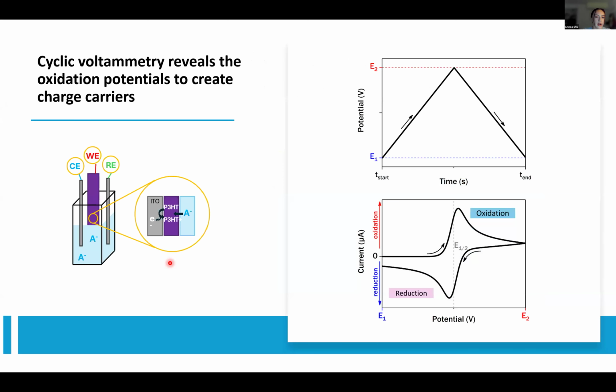So to do this, we can take our cell and perform experiments such as cyclic voltammetry, where we are sweeping the voltage and measuring the resultant current. And where we have peaks indicate the potentials at which we are oxidizing the polymer. So on the forward, our positive sweep, here we have the oxidation peak, and this is where we expect to see anion intercalation into the film. And then on the reduction peak, we expect to see deintercalation of anions or de-doping.